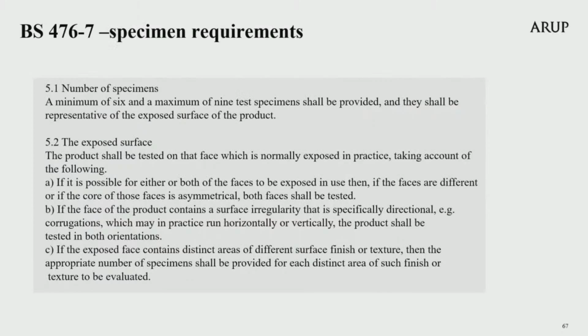However, there are a number of other requirements for the specimen, which I will briefly run through. A minimum of 6 and a maximum of 9 test specimens shall be provided, and they shall be representative of the exposed surface of the product. The product shall be tested on that face which is normally exposed in practice, taking account of the following. If it is possible for either or both of the faces to be exposed in use, then if the faces are different or if the core of those faces is asymmetrical, both faces shall be tested.